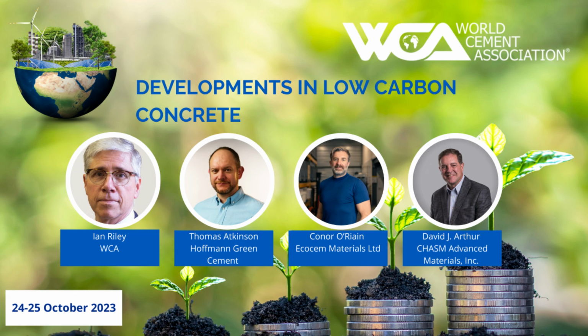But we soon realized that there's only enough GBS in the world, the raw material from the byproduct of the production of steel, to replace about 10% of the world's cement. So there isn't enough GBS to reduce the CO2 emissions of the cement industry in line with the IPCC's recommendation, which is that we need to reduce our carbon emissions by 50% by the end of this decade to avoid catastrophic levels of global warming. Basically, the cement industry is not on track to achieve this.